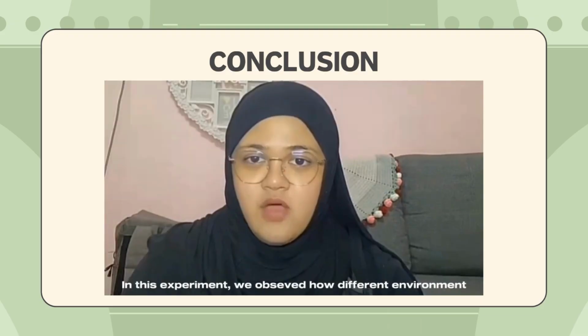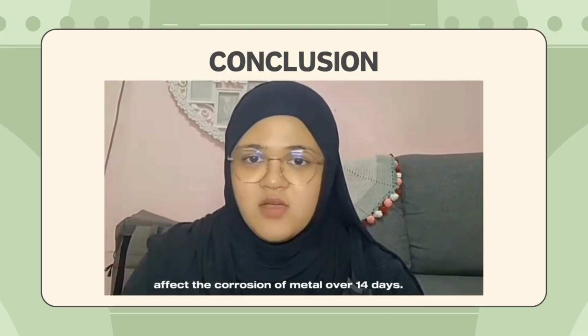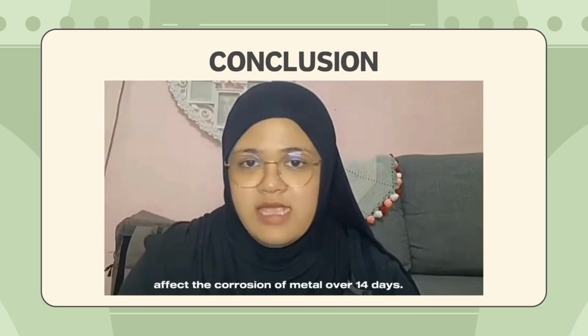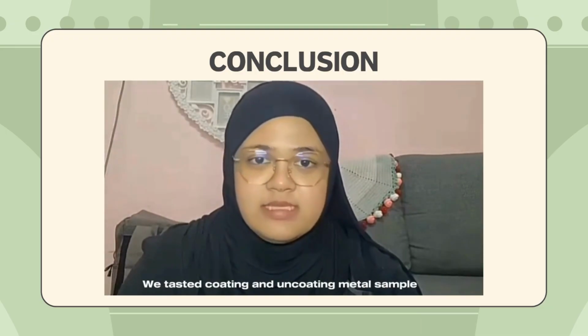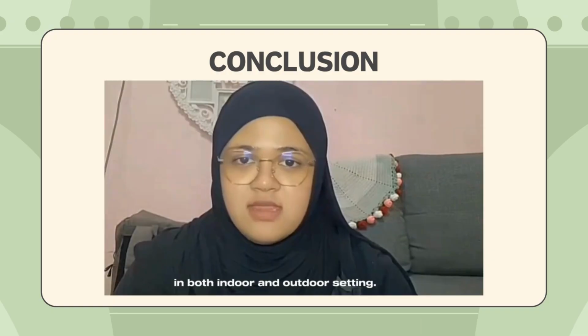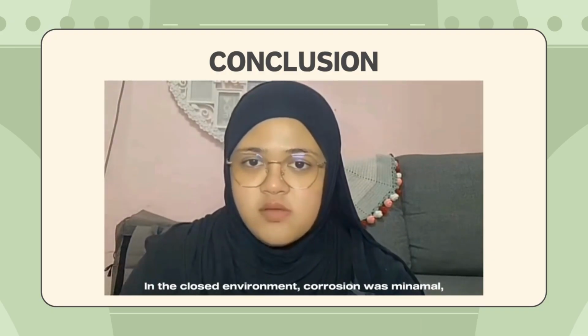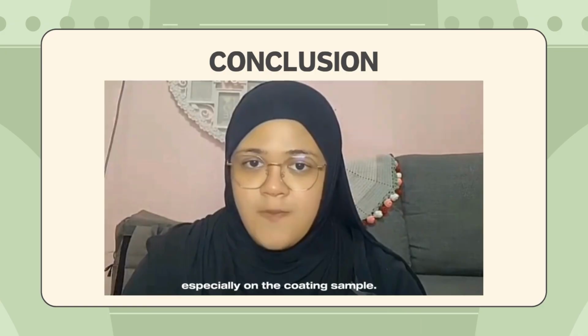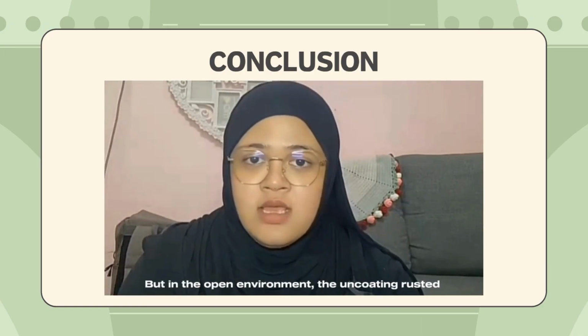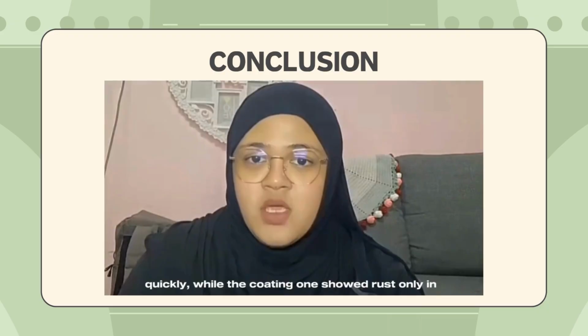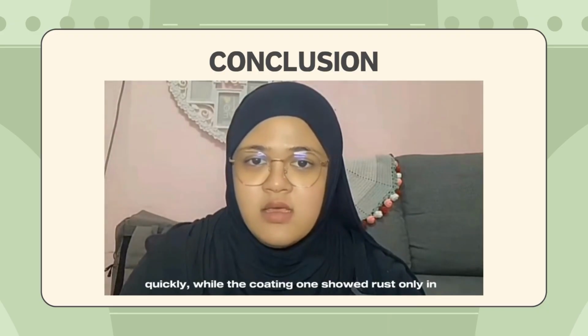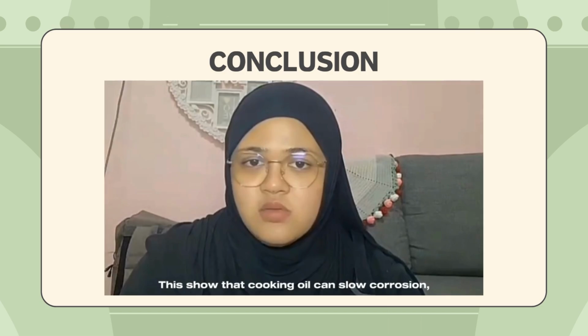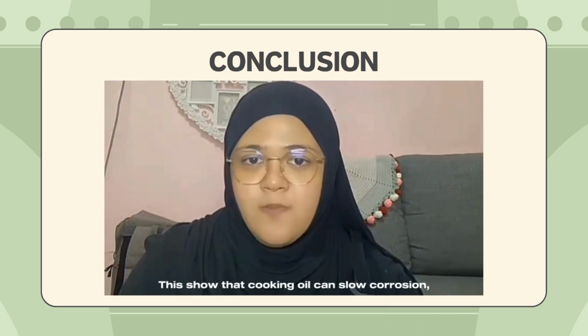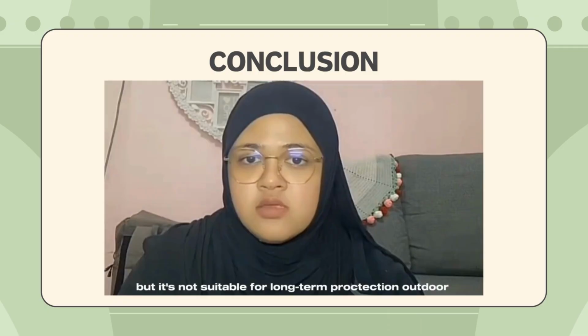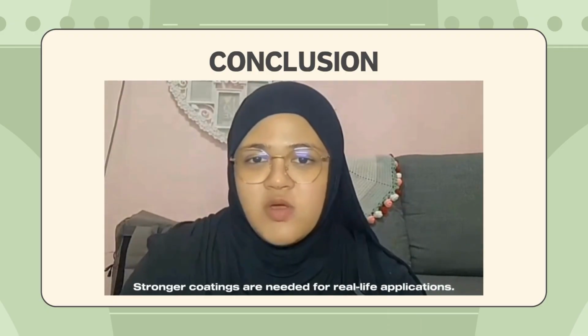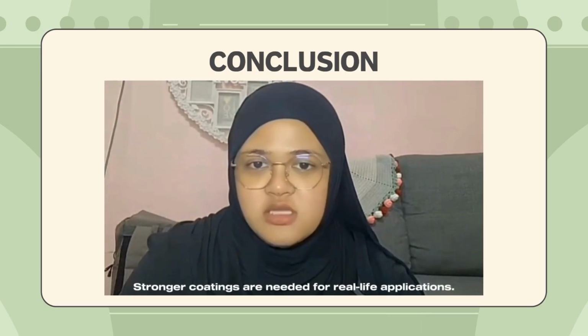In this experiment, we observe how different environments affect the corrosion of metal over 14 days. We test coated and uncoated metal samples in both indoor and outdoor settings. In the closed environment, corrosion was minimal, especially on the coated sample, but in the open environment, the uncoated sample rusted quickly, while the coated one shows rust only in certain areas. This shows that cooking oil can slow corrosion, but is not acceptable for long-term outdoor protection. A stronger coating is needed for real-life application.